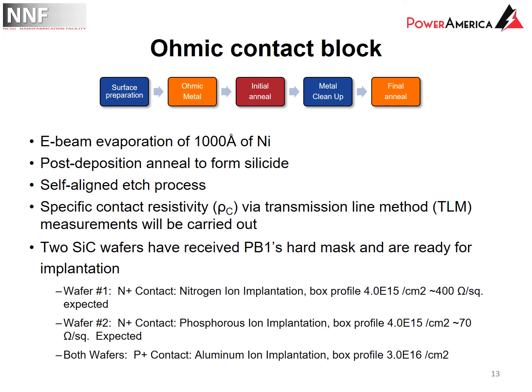ohmic contacts. The most challenging part of this process is actually going to be the ion implantation, which is something we can't do on campus. We need to go ahead and have this outsourced. So we've identified the vendor for this. We've sent the vendors the wafers and the implant schedule, and we're in the process of getting that work done. Afterwards, we will go ahead and do an anneal, a high temperature anneal, to activate the dopants and then wrap up the ohmic contact block, which will also mean that we'll wrap up the project which NNF has enjoyed working on thoroughly.